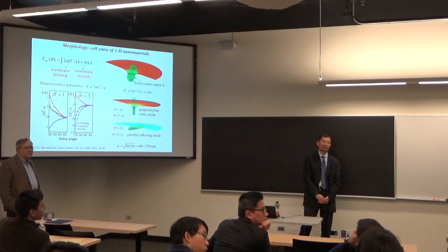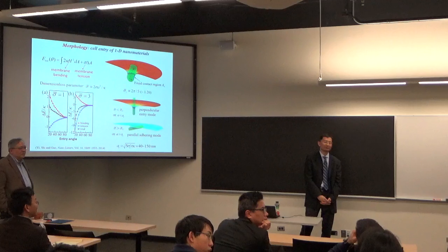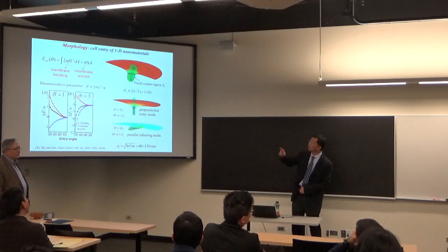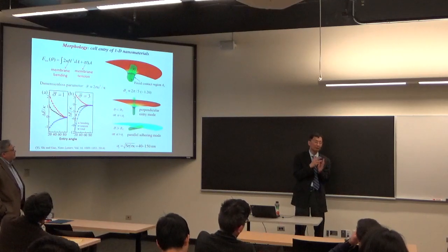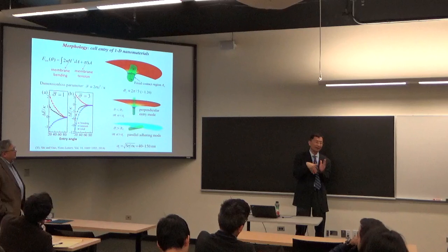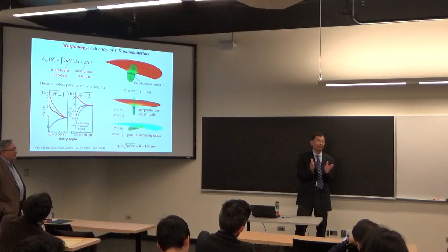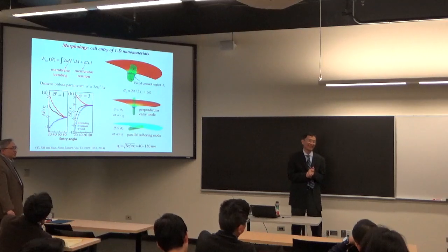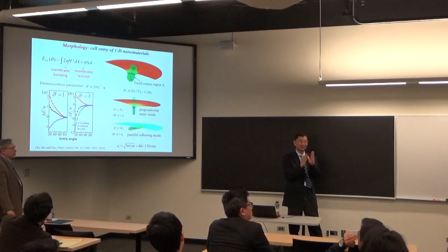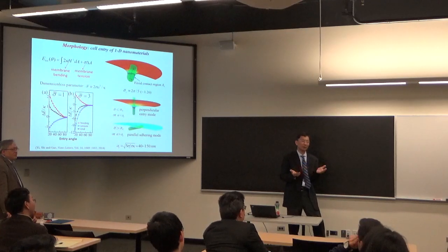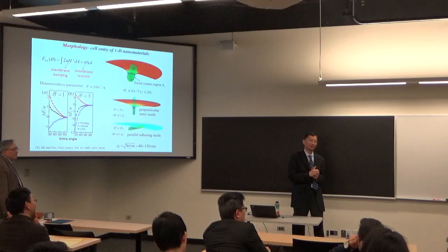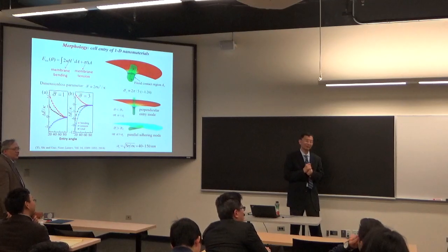So in this way, the nanomaterial is surface modified? Yeah, the surface modification is included in our model with the contact area change. It plays a very important role, because the free energy associated with the interface is the binding energy times the contact area. If the contact area is constant, it doesn't play a role. We're minimizing energy to determine which configuration, which mode of cell uptake. But if you ask how fast the cell uptake process is, then the binding energy plays a very important role. It depends on which question you are interested in.